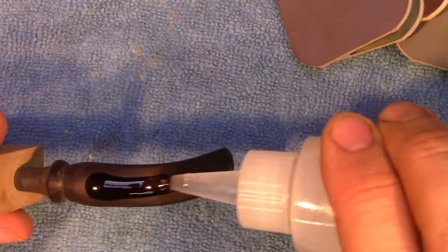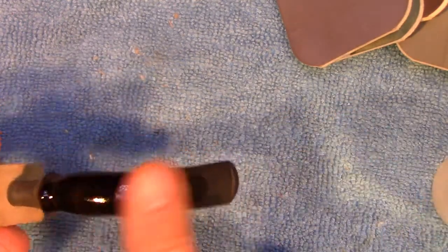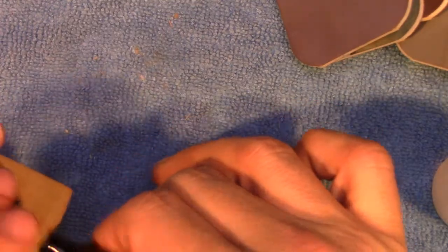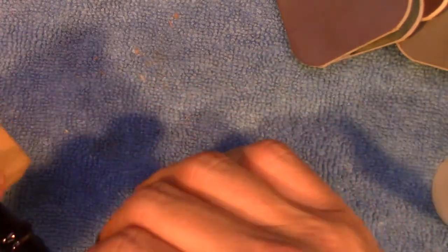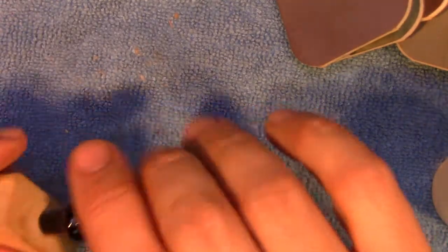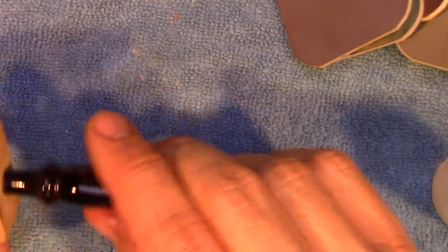What I'm going to do is coat this in mineral oil. The reason I'm going to do that is I have just opened up a bunch of new, fresh ebonite surfaces that may be ripe for oxidation, and I want to protect those. I also want this to sink in a bit, and it will help me lubricate things for the next sanding.